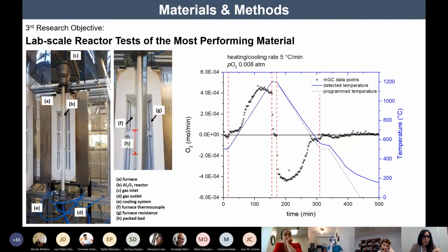And tested the pellets in the laboratory scale facility that is reported here in this figure, which mainly consisted of an alumina reactor and a furnace. The exhausted gas was analyzed through a MicroGC analyzer, and several reduction oxidation cycles were run. This is a typical example of a temperature program that was run.